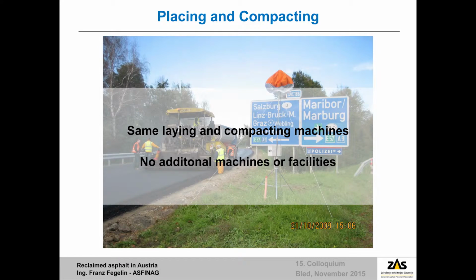For placing and compacting, there are no differences between material with or without reclaimed asphalt. As for the compacting, our personnel manning the machines reported that the time for carrying out the compacting was a little bit shorter in this case than with normal asphalt mix. This was confirmed by means of measurements carried out on the site.